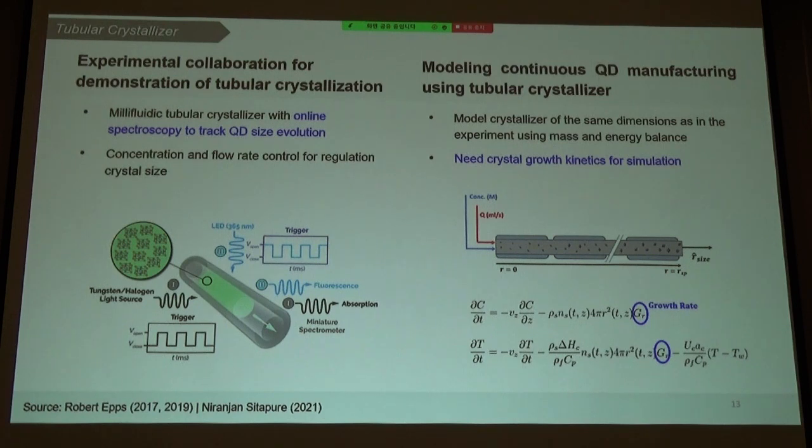along this crystallization reactor, which is about 1 meter. They first measure the light intensity, and because they have already constructed lookup tables, they can calculate the corresponding crystal size and so on. So basically through that kind of sequential approach, we were able to have a real-time measurement of the crystal size while they are growing.